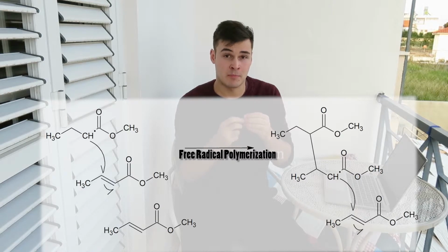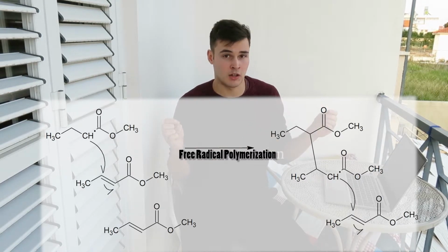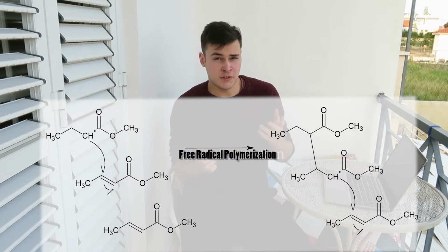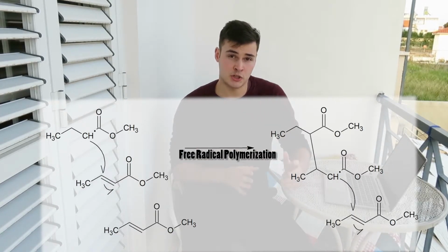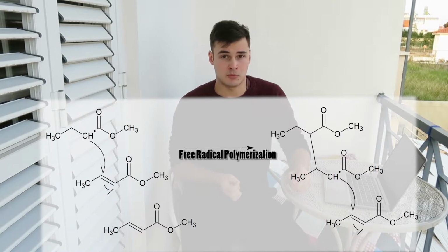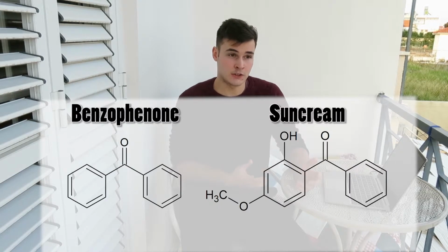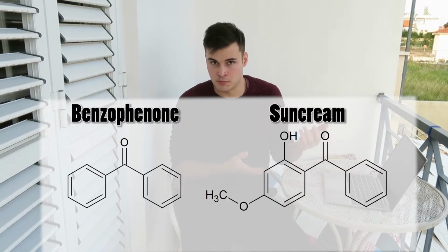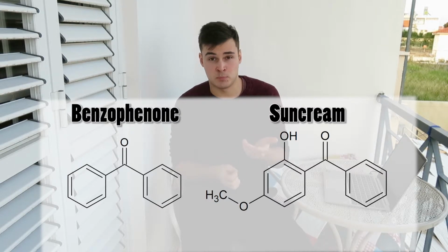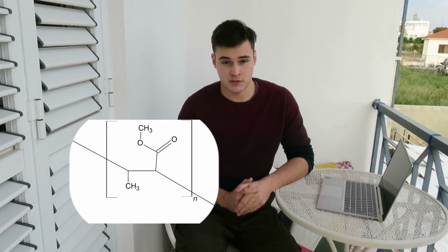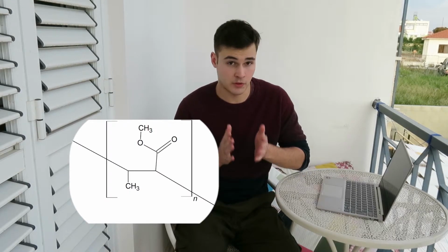Like in any polymerization process, in photopolymerization, monomers add together to form high molecular mass chains that yield a hardened material we call plastic. The difference here is that they're not initiated by high temperatures and unstable compounds, but are aided by light. Hence, the photoinitiators are much safer to store, such as benzophenone, a sunscreen derivative, against the more traditional AIBN that almost burned down a Japanese chemical plant. I'll be talking through the process of making polymethyl methacrylate via photochemistry in the general context of CLIP.